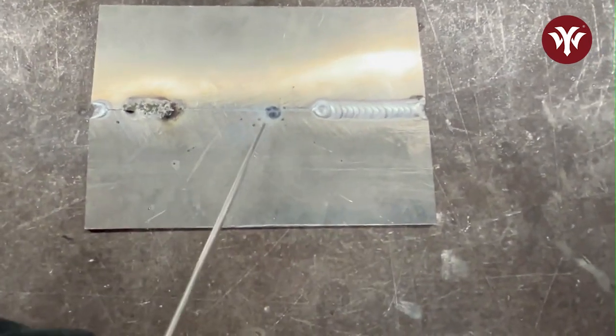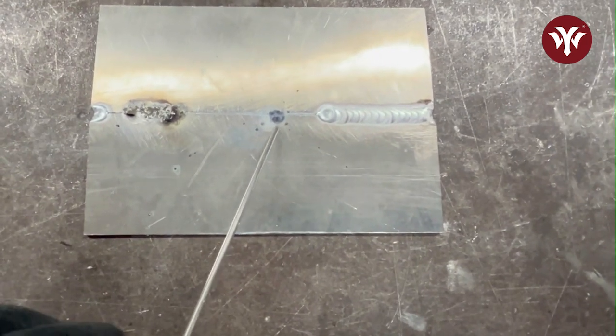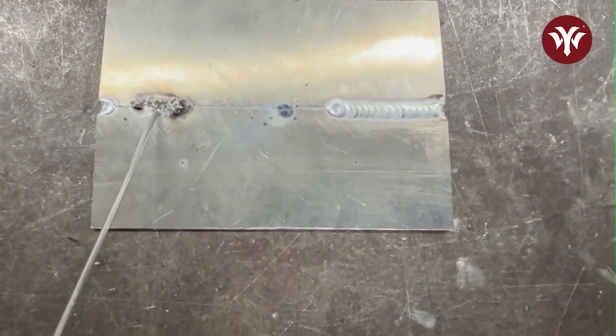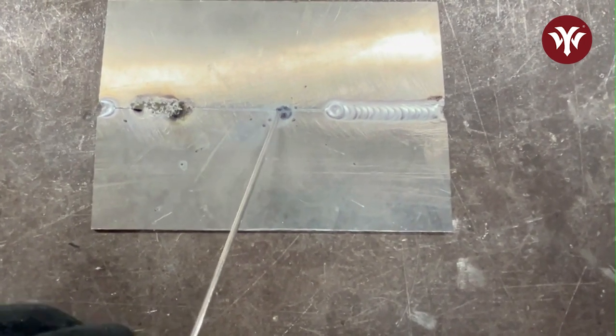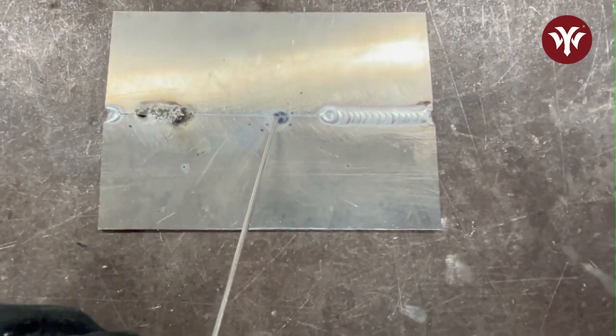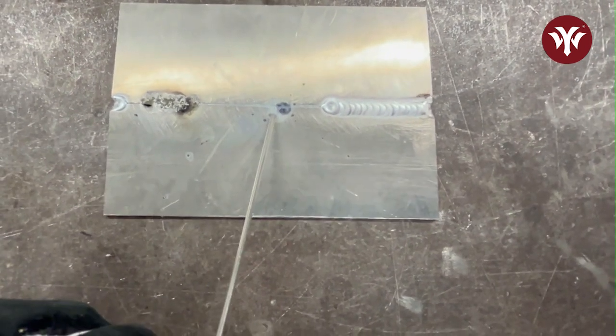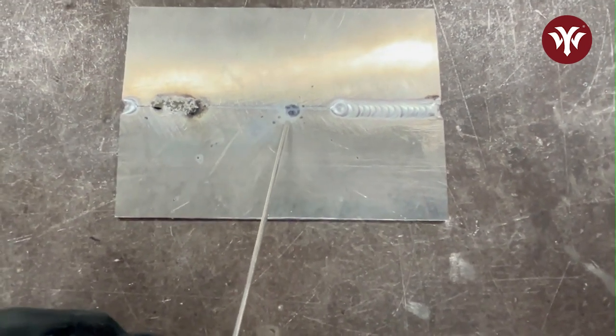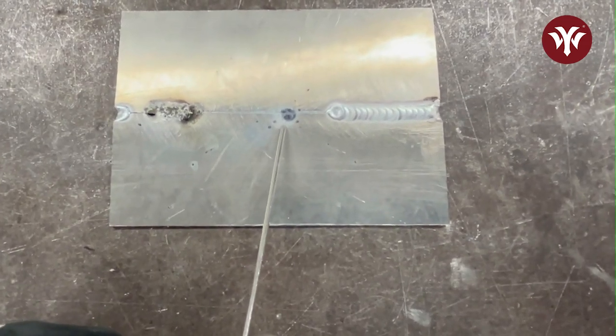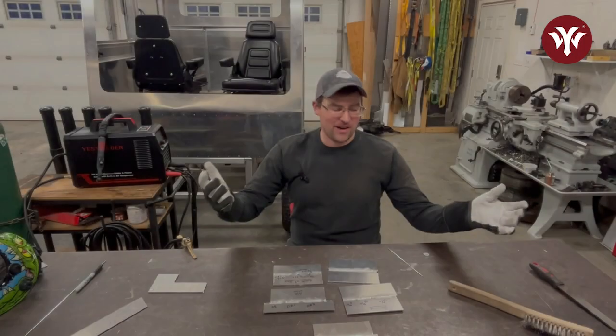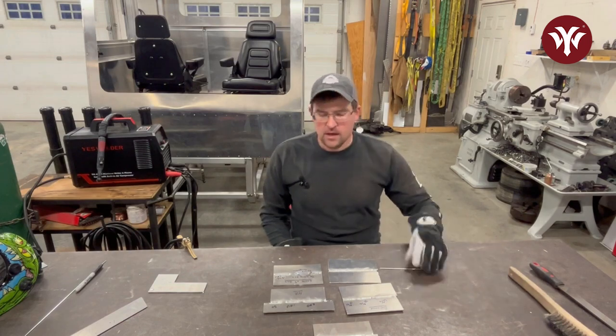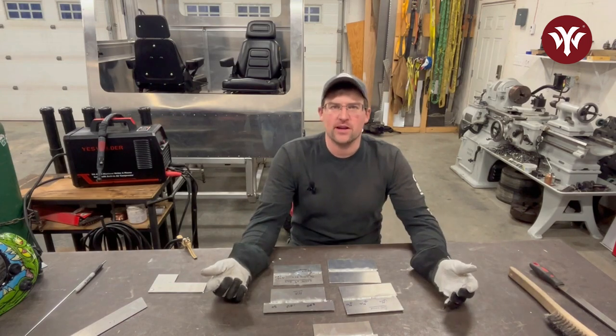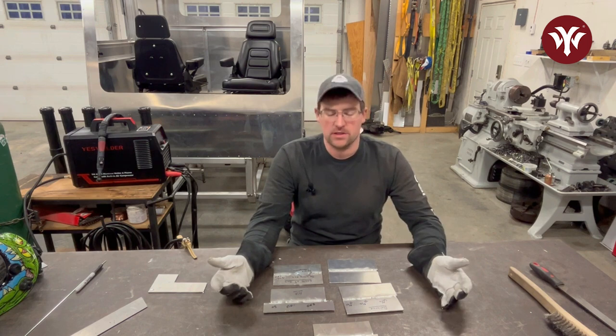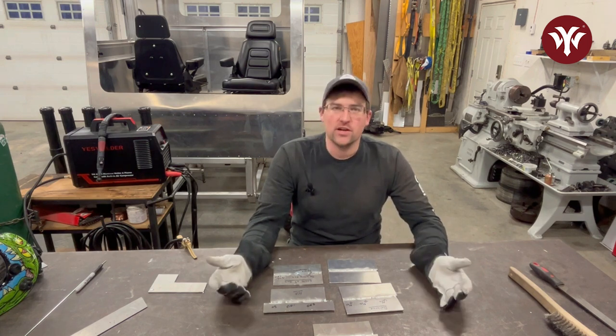So if you're getting welds that have a lot of soot in them, or just don't seem to have good arc control, or your tungsten is turning black and burning up, you probably have a gas issue and contaminants getting into your arc or weld zone. All right, well, I hope you've gotten enough information out of there to get out and start practicing some of this yourself. It's really not that hard. It just takes some time and experience.